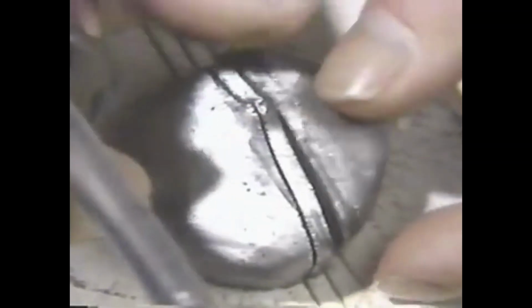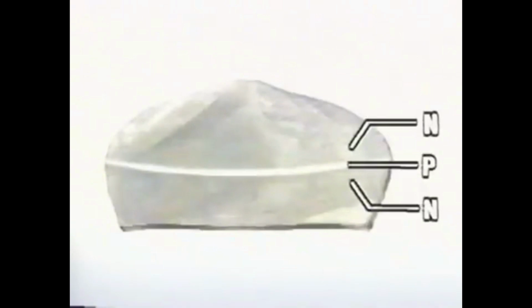These are seed crystals that were actually drawn. After they cool off, the crystals are extracted. In the middle of this mass, a p-type layer has formed. This is finely cut into slices. When we plate one of these slices, a white line appears. That's the p-type layer. Sandwiching it from above and below are the n-type layers.